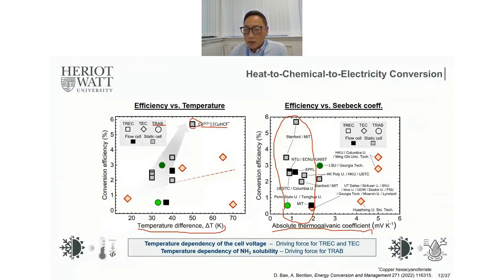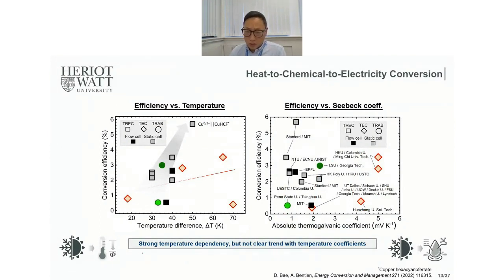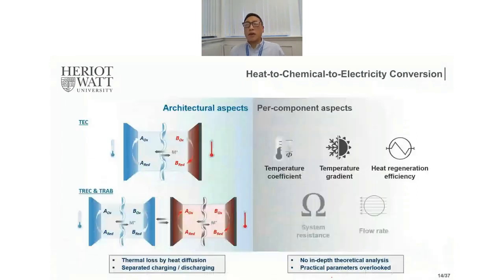In this case, the thermoelectrochemical cells have a very high Seebeck coefficient, but still the conversion efficiency is only between 1 and 3. Shortly, there is a strong temperature dependency, but no clear trend in the temperature coefficient. It is basically because all these cases I have shown in the previous chart are at a very low technological readiness level, which is lab scale, and the engineering specs are all not mature and not well designed.